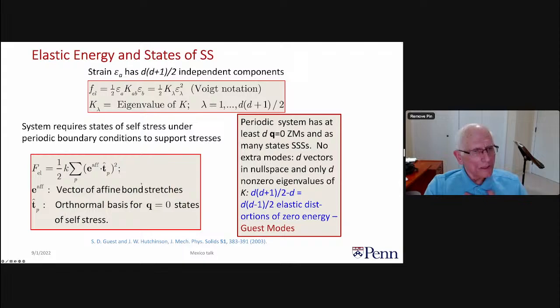And it turns out that the expression for the elastic energy is really quite amazing. An affine transformation is one where you set a new position R prime of site R equal to a constant matrix lambda times R for every R in the sample. That's an affine transformation, and your usual long wavelength elastic energy is in fact for an affine transformation. And what the energy actually is, if I have just a single elastic constant, is E affine dotted into the orthonormal basis for the q equals 0 states of self-stress, and you can prove all of that if you wish. Okay, I think I will stop there.